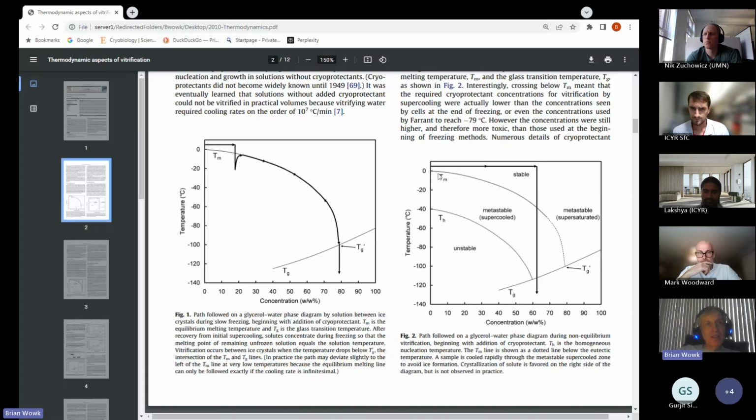And you find that it's pretty independent of the solute, actually. And so at low concentrations, it would make sense to plot in terms of moles. But once you start getting to higher concentrations, the melting point becomes a non-linear function of the number of moles and even the percent concentration.